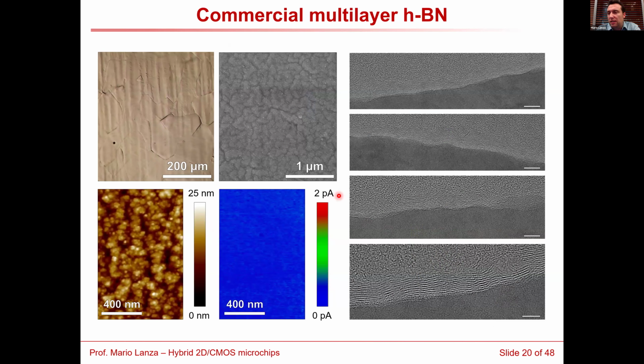However, our devices, the ones that switch well, are made with CVD grown multi-layer hexagonal boron nitride. And this is a sample that looks like this. This is the optical microscope picture where you can see the boron nitride on the polycrystalline copper foil. If you take SEM here, you see something like this.